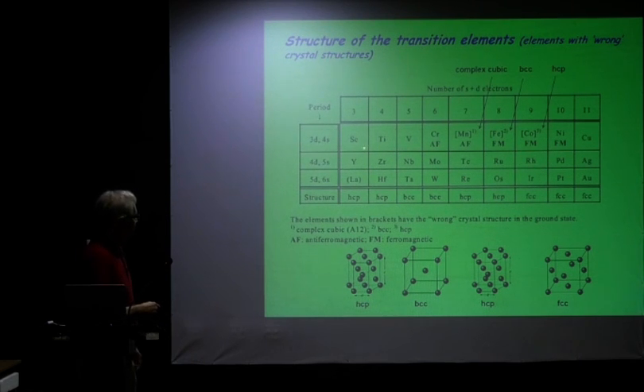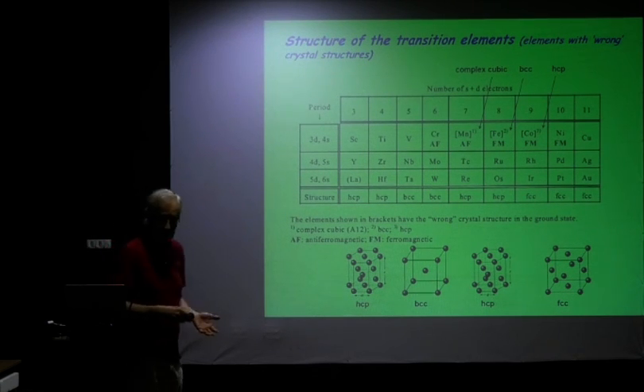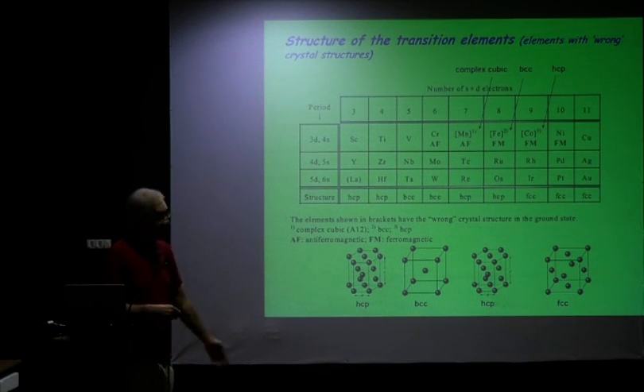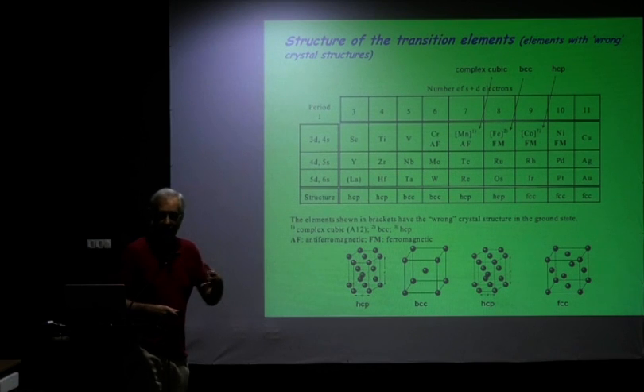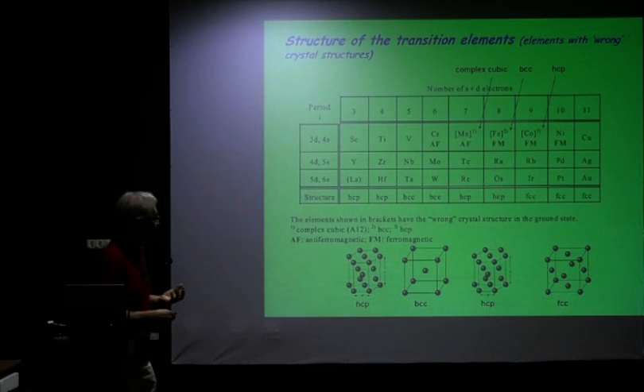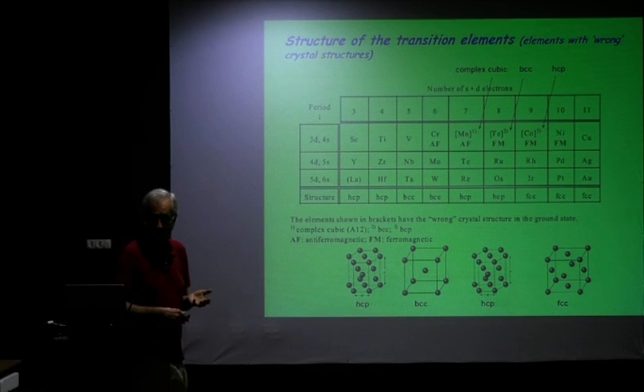When you look at the 3ds, they also follow this up to chromium, but these three here deviate. This becomes a complex cubic, this becomes body-centered cubic, and this becomes hexagonal instead of FCC. And then in nickel and copper, everything is normal again. So something happens, and we say that these three elements have, at room temperature at least, the wrong crystal structure. They should be something else. What should they be? Manganese should be hexagonal. Iron should be hexagonal. And cobalt should be face-centered cubic.